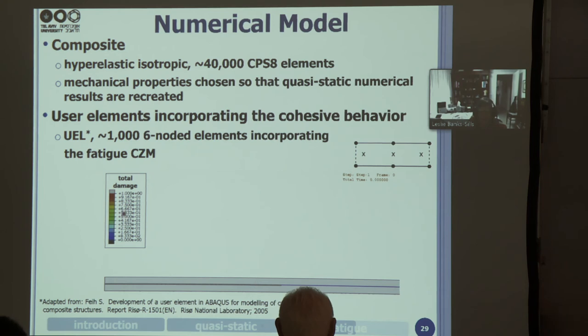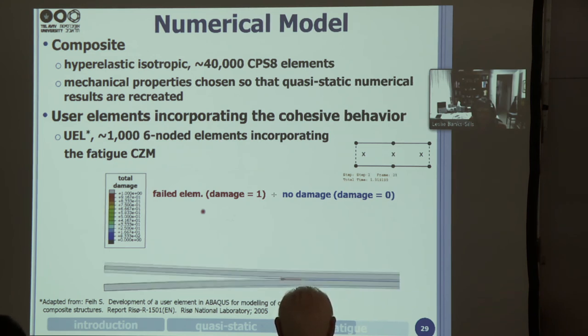And we're going to look at the damage. So the damage being one means that the fibers are breaking. And when the damage is zero, there's no effect here. You can see we have damage, which is zero. There's no effect on the model. And so the failed elements, damage is one, no damage is blue. And you can see now we carry out in finite elements the fatigue propagation. And you can see that these are the broken fibers. You can see the cohesive zone. And there's a fiber bridging zone within the cohesive zone.